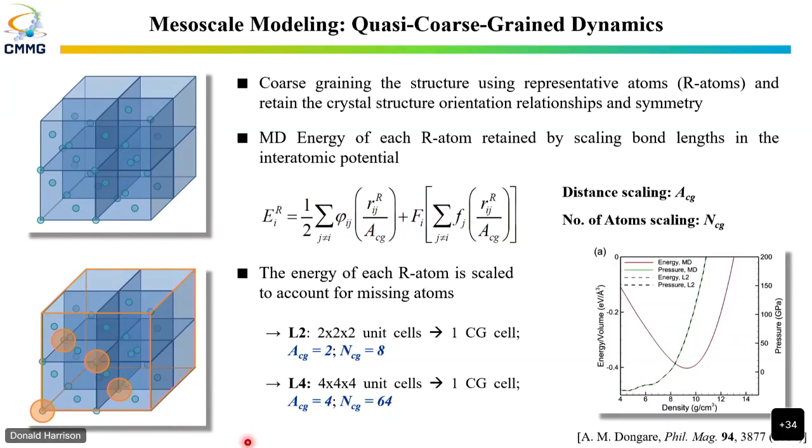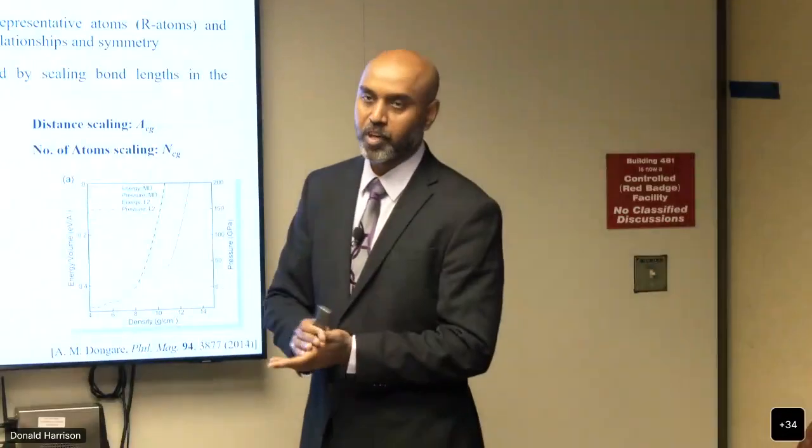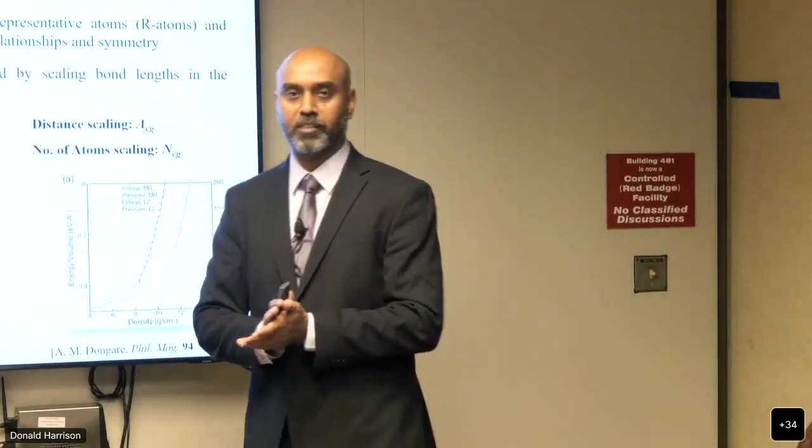So instead of 10,000 dislocations, our coarse grain model will roughly have maybe a few thousand dislocations. But that scaled energetics accounts for you to get the same stress released due to nucleation of dislocations, and we are able to reproduce the full dynamics of the shock wave while this is happening. So I'd be happy to talk to you separately on this as well.